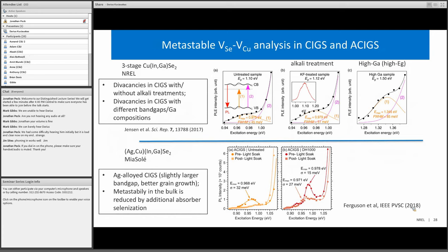They are also seen in CIGS that has the silver. An addition of silver to CIGS is a kind of recent development that offers important advantages. It has a slightly bigger band gap, so slightly better overlap with the solar spectrum, as well as somewhat different crystal growth. It allows growing larger grains using a simpler manufacturing process. And the silver CIGS is actually now a part of a commercial product.